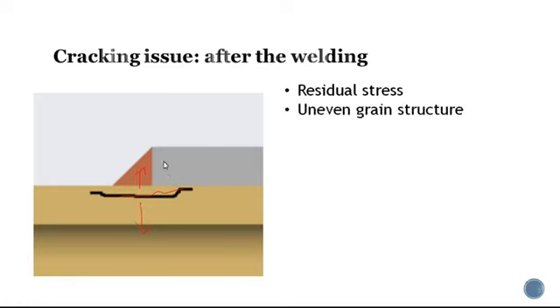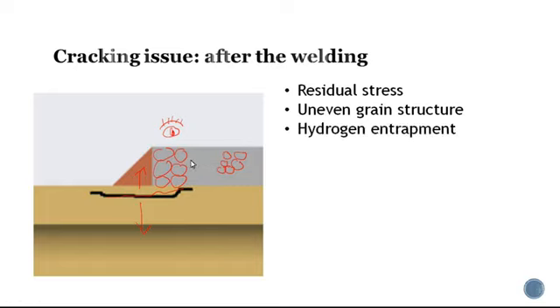There is also uneven grain structure because of the cooling near the weld area and further from the weld area. If you see the microscopic structure near the weld area and further from it, it is different, and that also causes uneven structure internally. Sometimes if hydrogen is entrapped and there are residual stresses because of the cooling, that is also one of the major reasons for cracking.